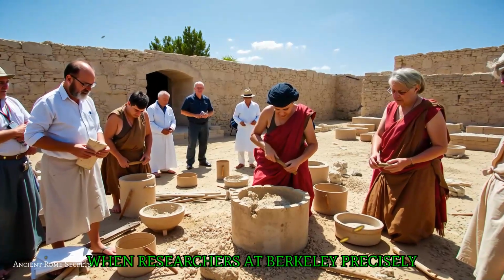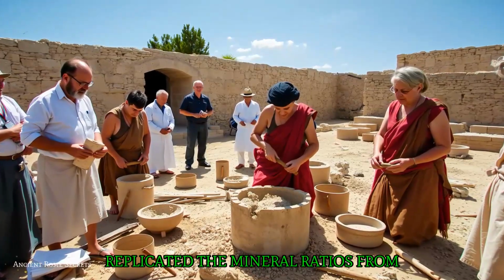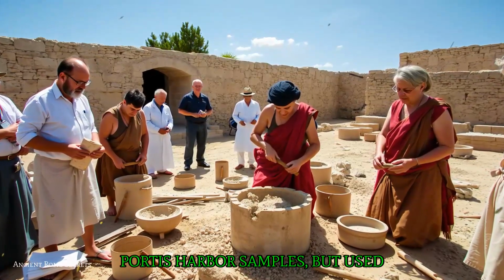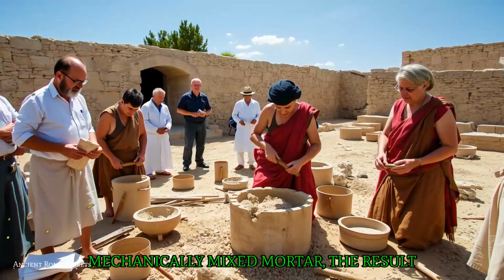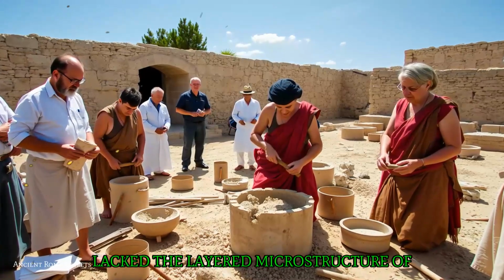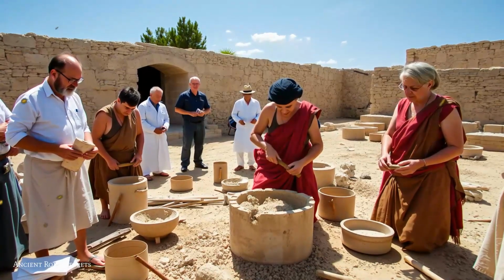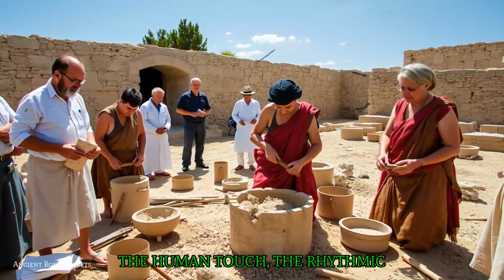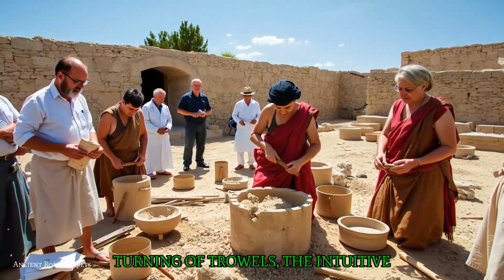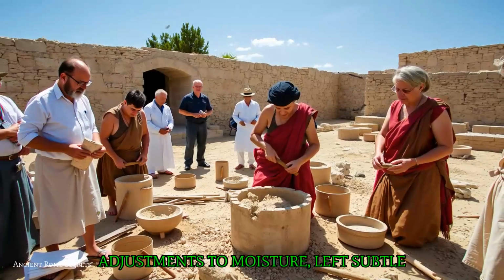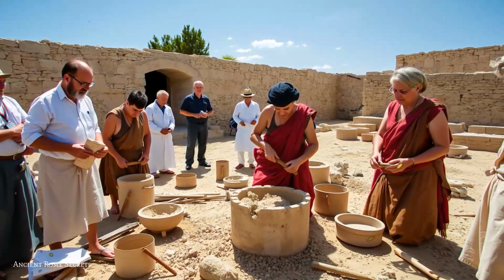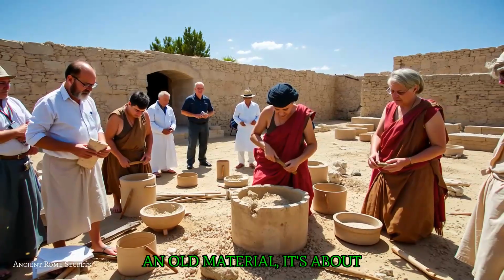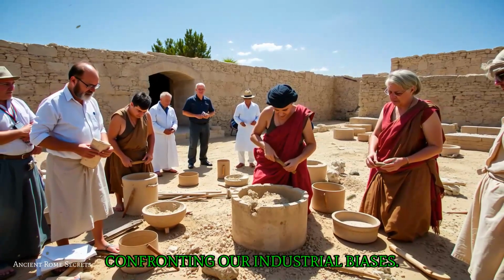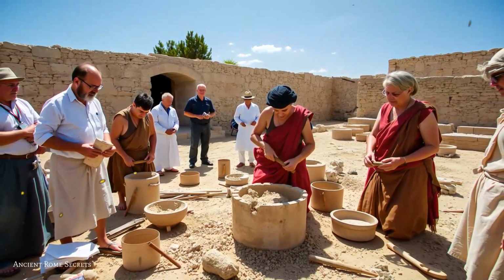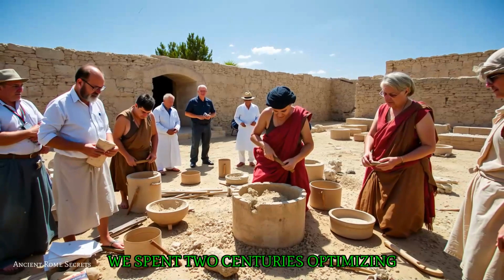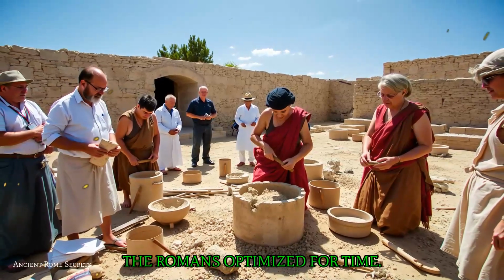When researchers at Berkeley precisely replicated the mineral ratios from Portus Harbor samples, but used mechanically mixed mortar, the result lacked the layered microstructure of hand-mixed ancient concrete. The human touch, the rhythmic turning of trowels, the intuitive adjustments to moisture, left subtle gradients that machines can't replicate. This isn't just about resurrecting an old material, it's about confronting our industrial biases. We've spent 2 centuries optimizing for speed and scale, while the Romans optimized for time.